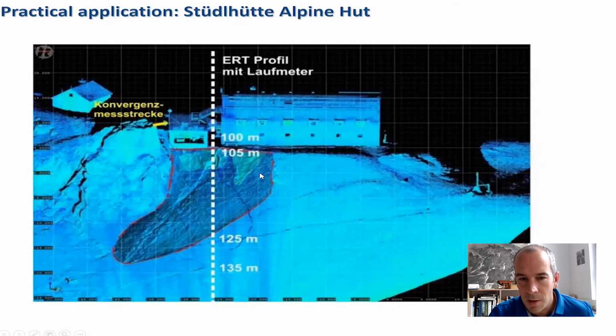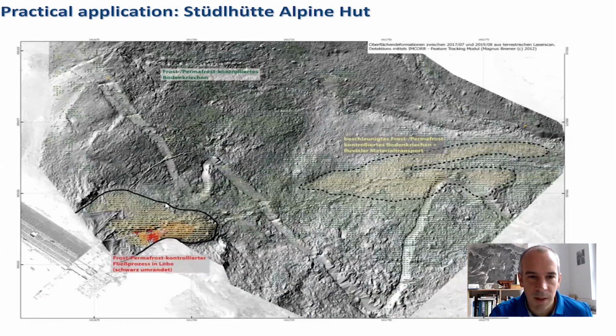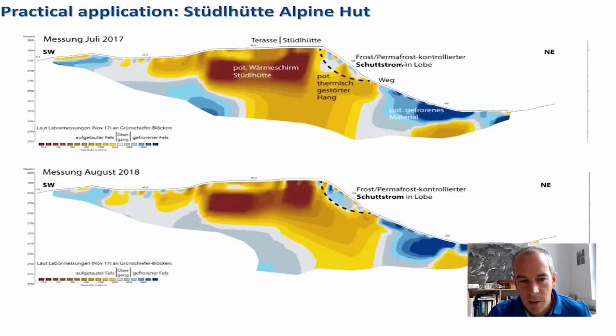On the laser scan, you can easily see from the surface pattern of the roughness the big movement we get in here. And we also did ERT profiles to see the thermal state. With that, we can first generate deformation patterns. You see we have deformations of 50 to 70 centimeters in the 2 recorded years, just below the hut in this permafrost-supported solifluction lobe. And the second thing we can do is look with ERT at the reason for this. And we see that this hut above has created a significant warming bulb under it, which is 10 meters deep. And also close to the hut, the northern face, which should be frozen, is not frozen anymore.